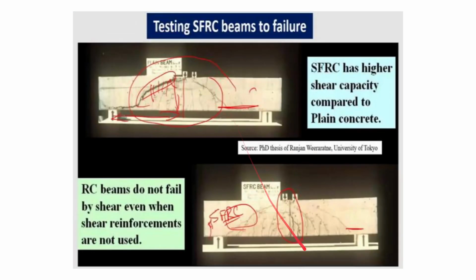So as you can see, if you compare a plain beam and a SFRC beam, SFRC beam has a higher shear capacity compared to plain concrete because of the fibers, and RC beams do not fail by shear. This we will not see here in this case. Even when shear reinforcement is not used, because of the fibers, they increase the tensile, shear, flexural capacity and also the toughness.